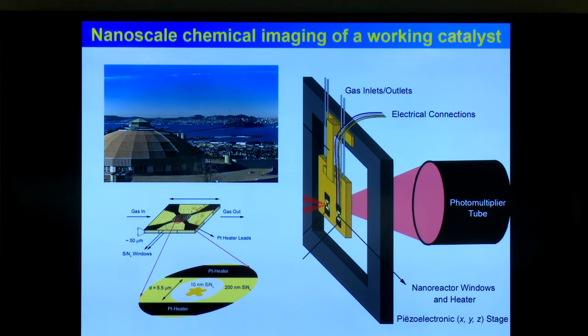Sorry, Frank, if you're not going to show yields again, I have a question. On L edges of titanium oxide, did you see excitons similar to XANES? In EELS? You mean in EELS? In yields of... Yeah. The spectrum in EELS is completely identical to X-ray absorption. Yeah. I just wanted to know about the resolution of this. Oh, okay. You mean resolution-wise? Yeah, to make this analysis based on yields. Yeah. Resolution in EELS is also limited by lifetime now.